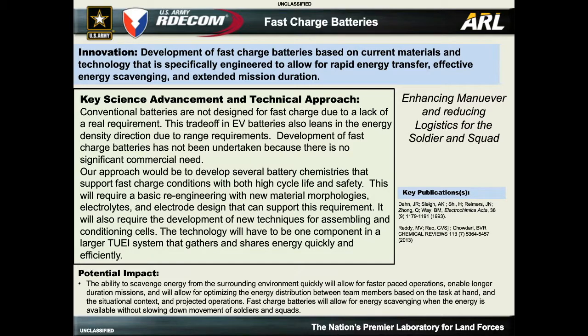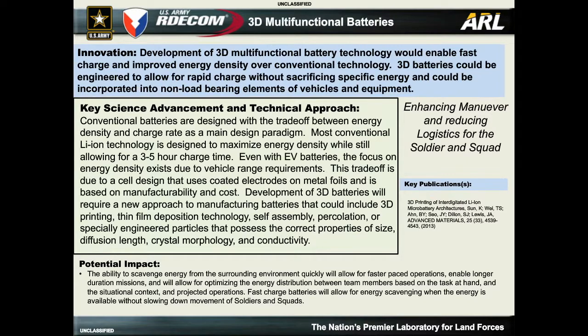So, in the longer term, the approach to get higher energy density is really to go to a 3D battery. And what does that really mean? That means that the diffusion lengths for lithium-ion transport need to be very short. And so if you look at conventional technology, what does that really mean? That means removing all of the porosity from the cell and shortening up the distance between anode and cathode material. So in the long term, I think that's where we will be working. And that should allow us to develop fast charge, high energy density batteries.